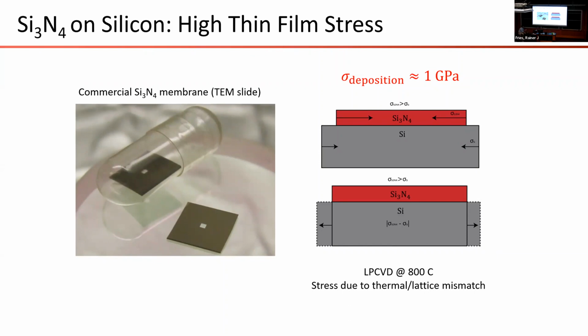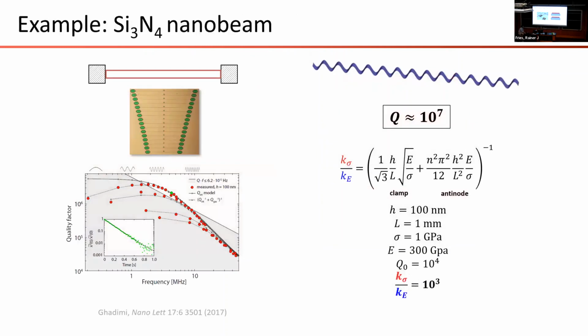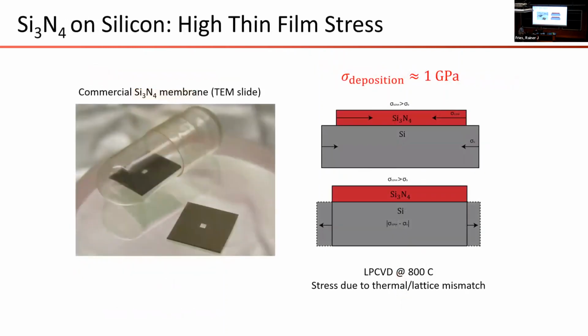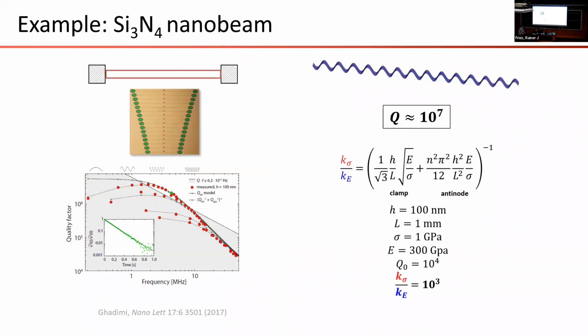If you work with transmission electron microscopes, it's a standard thing to see a released film of silicon nitride on silicon. It's just a transmission electron microscope slide. These devices intrinsically might have this dissipation dilution. Actually, we realized this purely by serendipity in the field of cavity optomechanics back in 2009. So I just want to show you a few examples of what you can do by basically etching these silicon nitride membranes or into beams.